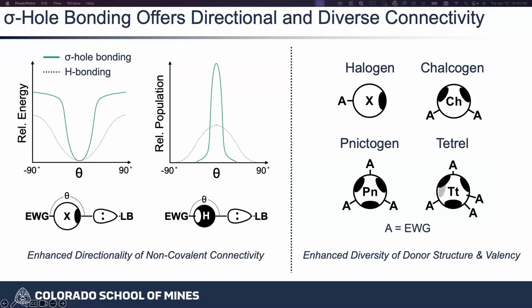We also have diversity. Protons are protons, hydrogens are hydrogens. But what we have here are 4 different groups of the table, 3 of which have been well explored. One's a little bit more theoretical. So in each one of those cases, we have theoretically 1 sigma hole for every covalent bond. And so a halogen, like an iodine, you have 1 covalent bond, 1 sigma hole. A chalcogen, like tellurium, you can get 2. Pnictogens, you can actually get 3, and that's been experimentally shown as well. So we have diversity, we have elemental diversity, we have valence diversity, and we have this directionality.